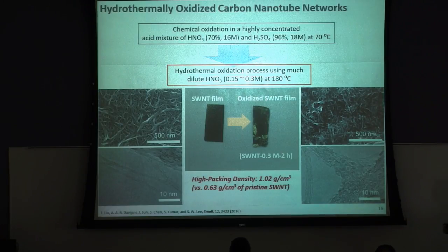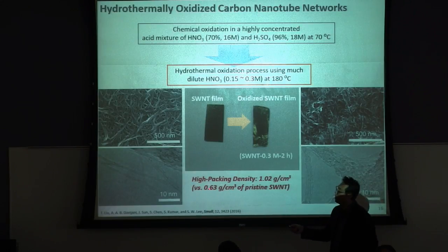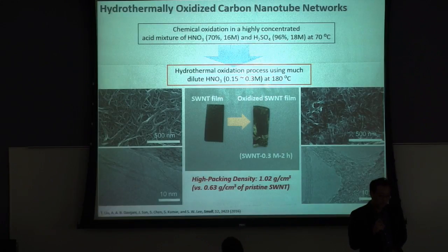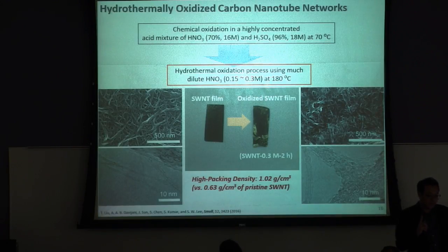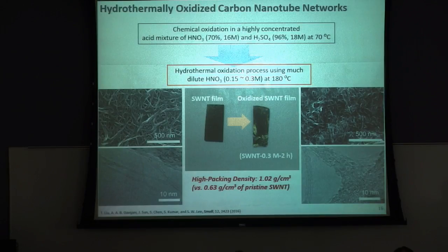One interesting thing is that the density also increases. The density of this single-walled carbon nanotube film is around 0.6 gram per cc, but after the oxidation process, the density has increased to 1 gram per cc. When we design electrode materials for energy storage devices, this density is also a very important engineering parameter. Can you guess why? Why is density important for designing electrode materials? To get high power density? Basically, we can get high energy and power density per unit volume of the device. If the density is high, we can make very thin or very small energy storage devices, right?